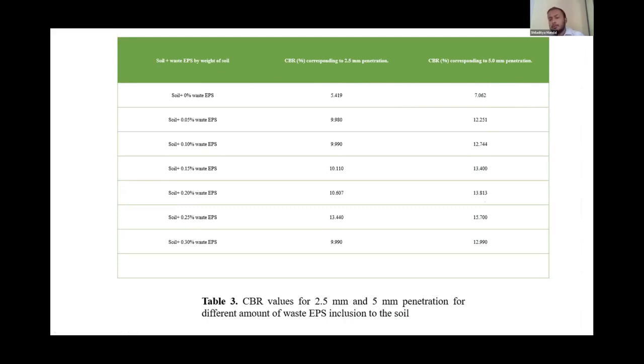And the reason being that whenever you get such a type of value, you're recommended to repeat the test so as to check whether there was a problem in the previous test. And we have experimentally repeated each and every test at least once after the main test to see whether our CBR at 5 is again coming greater than 2.5 or not. And since we got that confirmation that the CBR values at 5 mm penetration were greater, that is why we decided to use these values as the design CBR values and not the 2.5, which is generally considered.